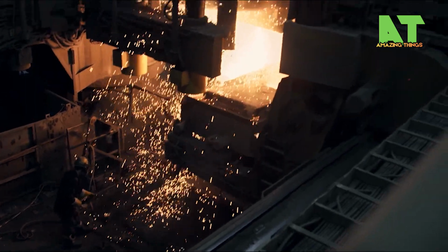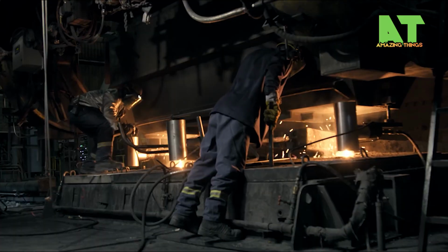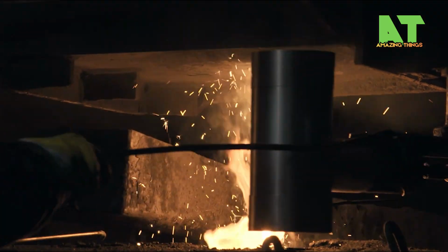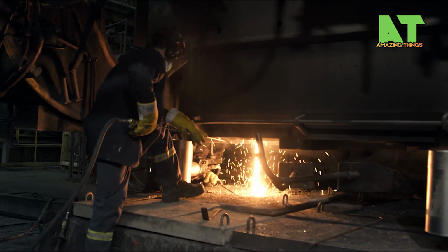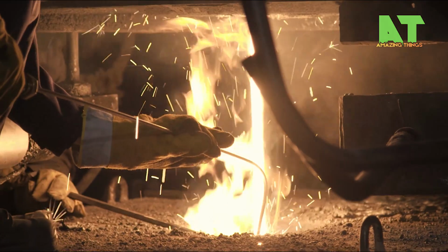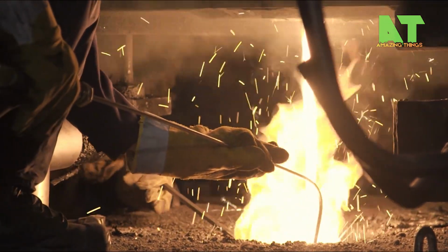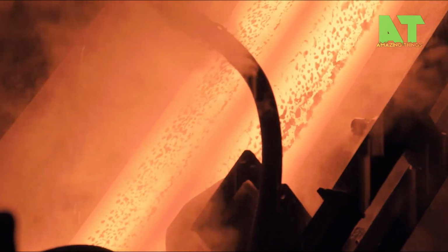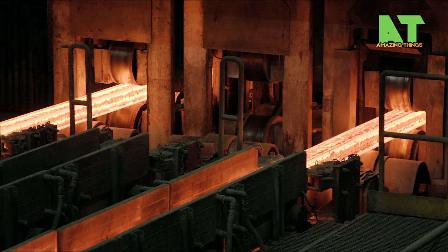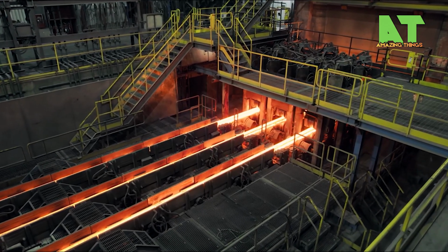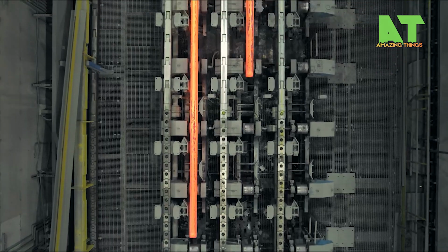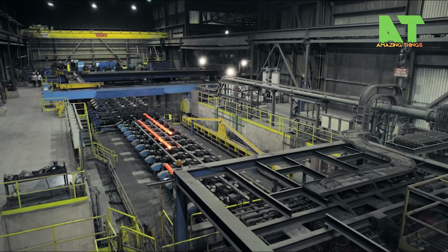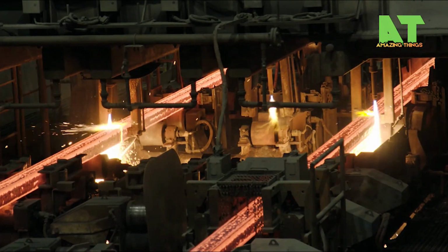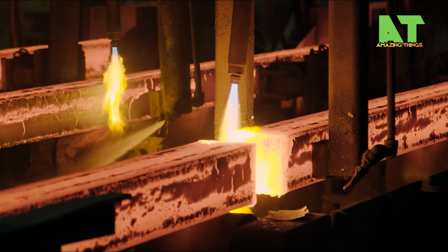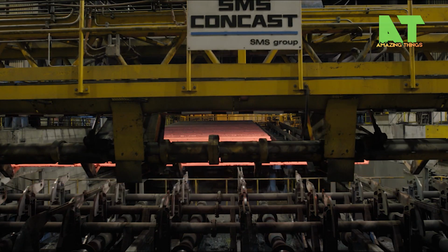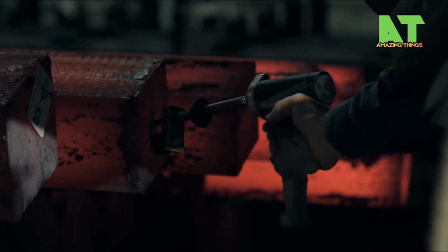Now here's where the magic really begins. Those billets get reheated in a walking beam furnace, a marvel of industrial engineering that slowly walks each billet through a controlled heat zone, bringing the steel back up to rolling temperature, around 2000 degrees Fahrenheit. Why reheat? Because steel at that temperature becomes workable, almost like very stiff dough, allowing the rolling mill to shape it without cracking. From there, the billet enters the roughing mill, a series of powerful rolling stands that progressively squeeze and elongate the steel. Each pass reduces the cross-section and increases the length.